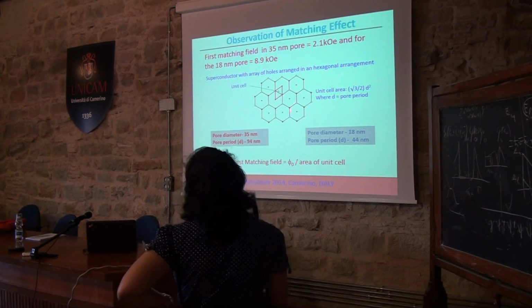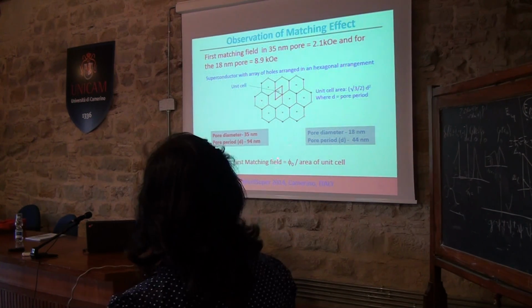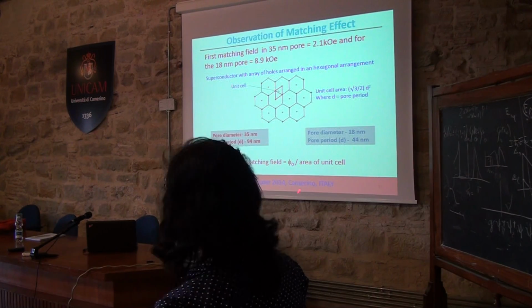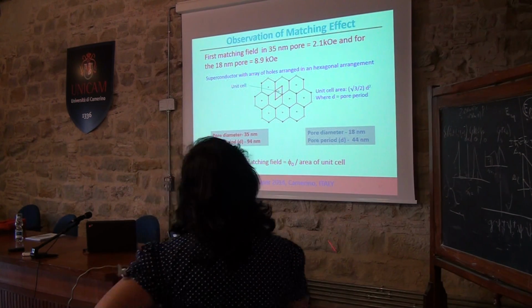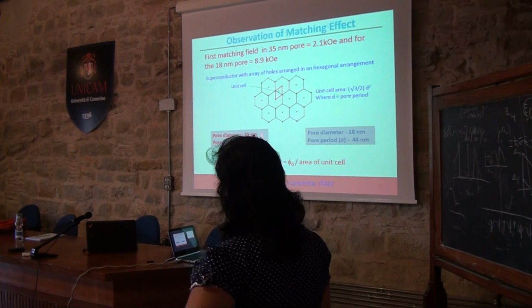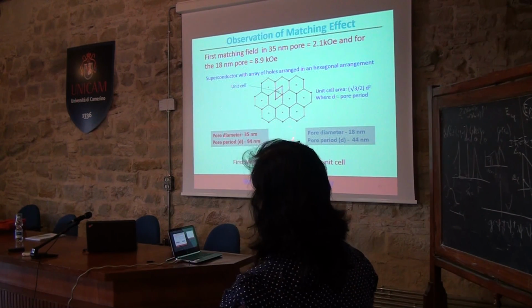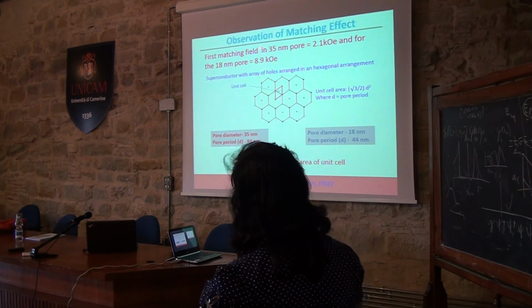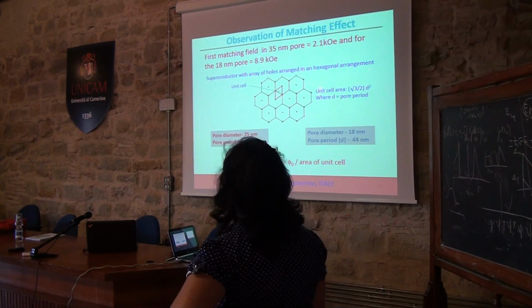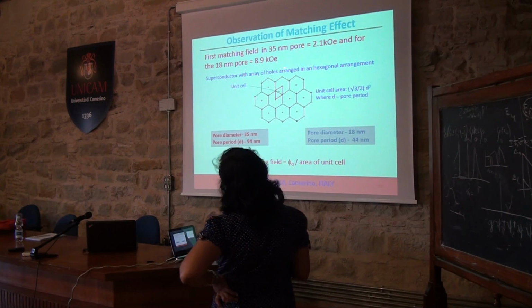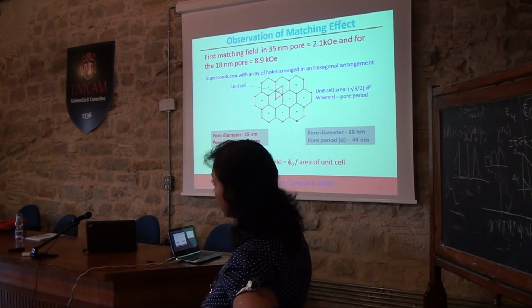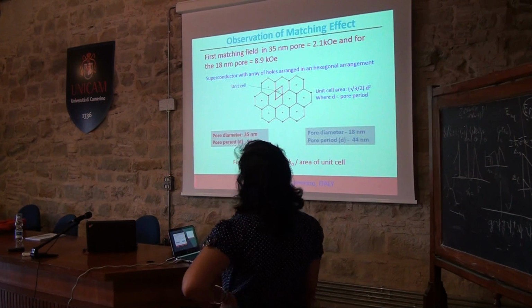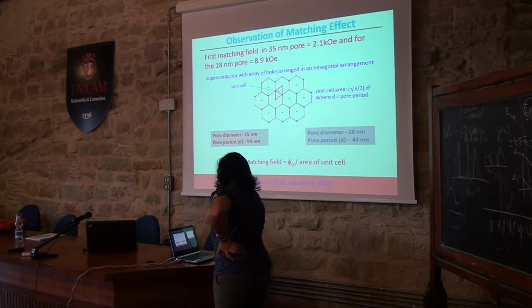Now to find out the matching fields, it's simple. The first matching field is nothing but the flux quantum divided by the unit cell area. So if you take the unit cell area for your two different systems, that is the one with 35 nanometer and 18 nanometer, it matches well with the first matching field which we have observed. For the 35 nanometer, it is around 2.1 kilooersted, and for the 18 nanometer, it is around 8.9 kilooersted.